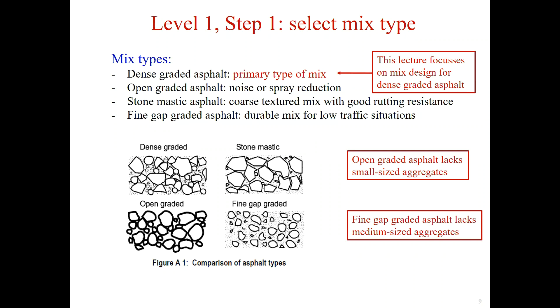The stone mastic asphalt is also a gap graded mix but with a high proportion of coarse aggregate, providing an interlocking stone skeleton that resists permanent deformation. Generally, it has high durability and high rut resistance.